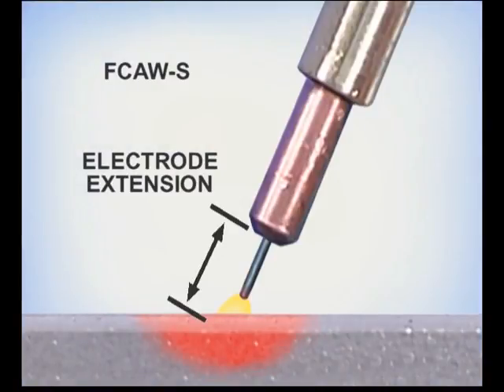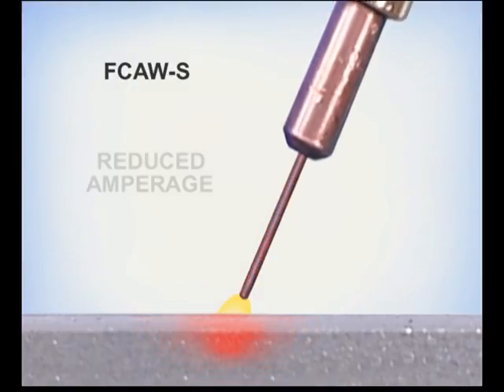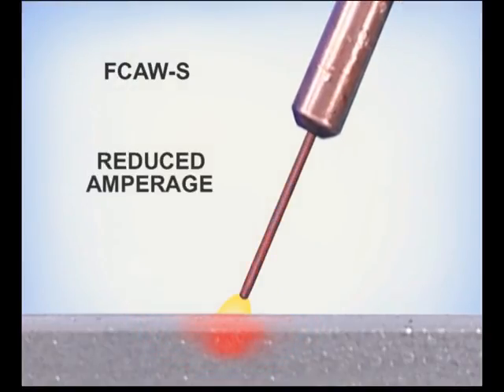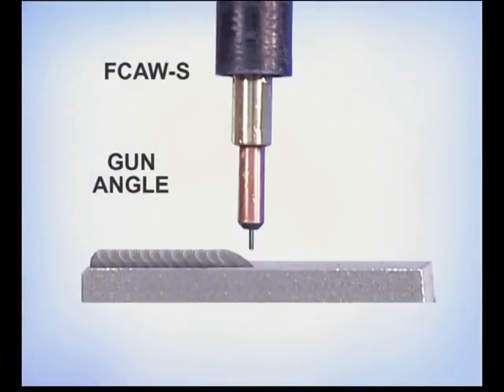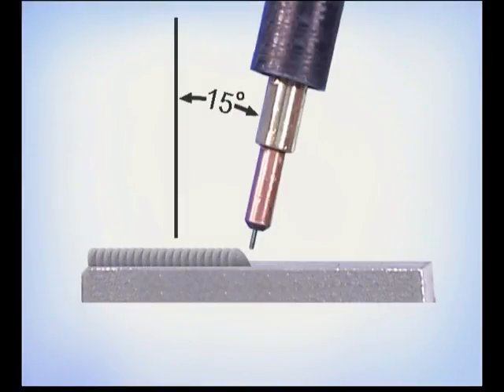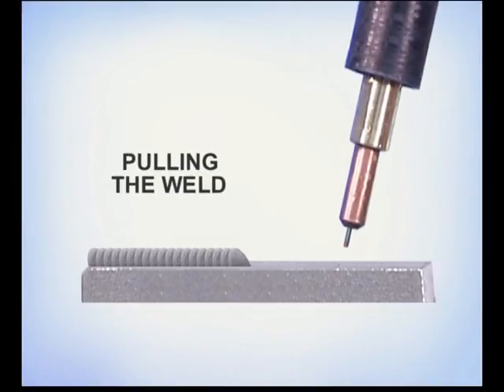While you want to avoid holding the gun closer, which can agitate the puddle, one of the unique characteristics of the self-shielded flux core wires is that you can back the gun away to fill gaps in poorly fit joints. You need to watch the puddle though, keeping it hot enough so the molten metal flows out on the sides. Under normal welding conditions, the gun can be held anywhere from nearly perpendicular to around a 15-degree angle back towards the weld. This is referred to as pulling the weld.